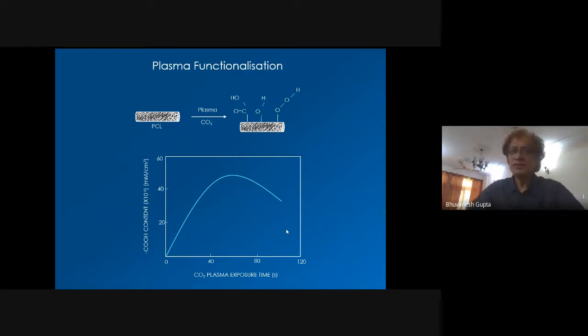So you can see over here in plasma functionalization, one example is PCL, polycaprolactone. This is, in fact, the PhD work of one of my students, Dr. Shameta. What she did, you can have PCL and you can use carbon dioxide plasma, CO2 plasma. And the CO2 plasma can give you carboxyl groups. You can see the time in seconds, 40, 80, 120. So maybe in 60 seconds, you get the maximum number of carboxyl groups. So instead of 2 hours, you are using 60 seconds, and you are getting carboxyl groups on the surface. And that's the beauty of plasma processing. Okay, next.